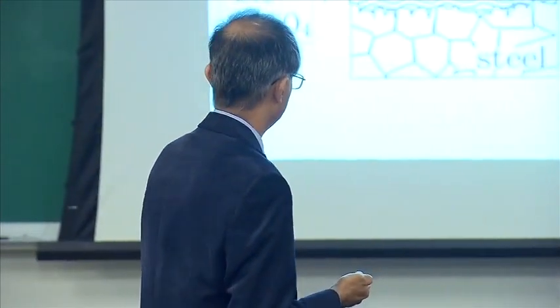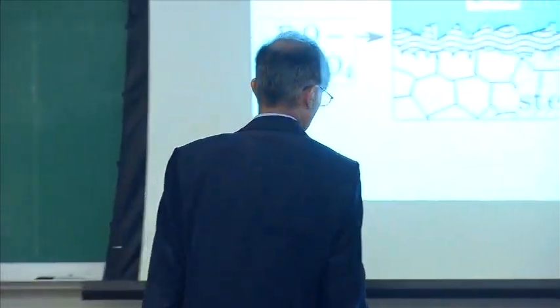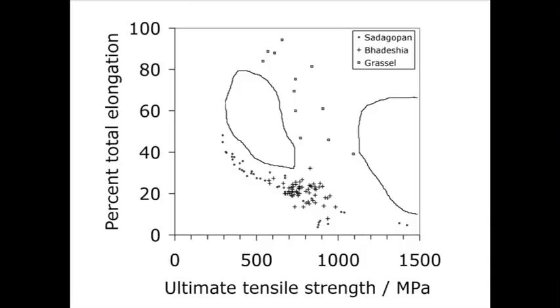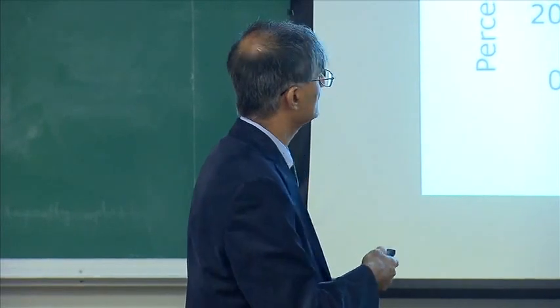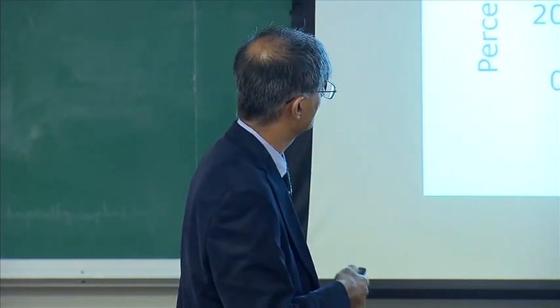So how can we solve this problem? Well, there's an awful lot of variables in producing this steel, and I'll just show you the properties that we are after. So if I take all kinds of automotive steels and I plot the strength and the elongation, so this is the elongation, which is important in formability, and this is the strength, you get the so-called banana plot. Yeah? That as you increase the strength, your ductility goes down. There are some special steels which are called twinning-induced plasticity steels, which are rich in manganese, which have a higher combination of strength and elongation, but they are actually very expensive. So we have these large gaps here, and if you can fill those gaps, then you would become rich.